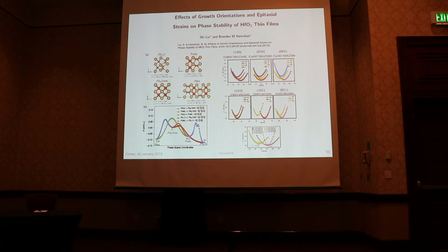So I'll kind of cut to the chase. I haven't even shown any of my results yet, but I think that once you stabilize or grow these polar structures, they're metastable, and it's really the growth conditions that are most important. So if you can rig things so that the polar phase forms, then you get a ferroelectric. And it's not that it's the most stable phase. It's not that the doping or the strain stabilized the polar phase, but rather that the growth conditions were such that it grew. And then once it grows, you have a polar system that can act ferroelectric.